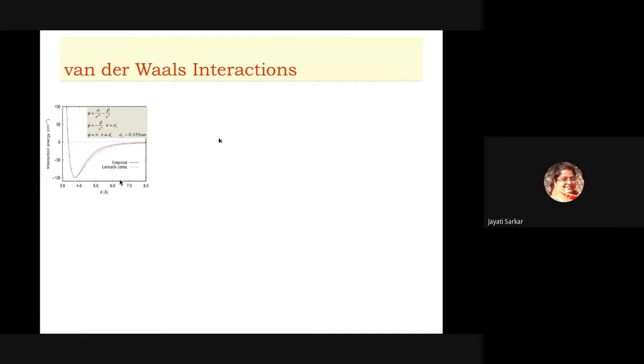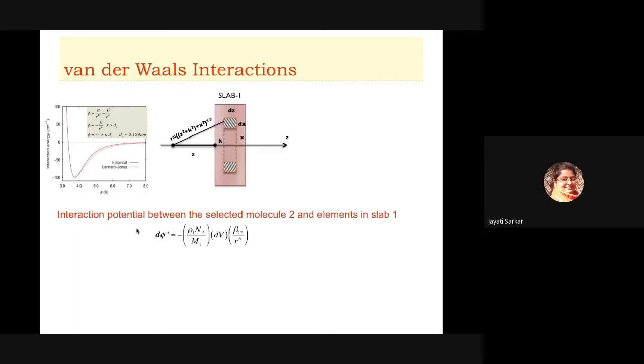So how do you think that even if the film is 100 nanometer, we are saying that if it is less than 100 nanometer, then excess intermolecular interactions come into play? But here, between the molecules, this force dies down very easily. So how is it valid across 100 nanometer? For that, we need to understand that this interaction is between two curved surfaces, or even between two flat slabs if we consider. So these are not between two molecules, but it is integrated between the two slabs where all the molecules are present.